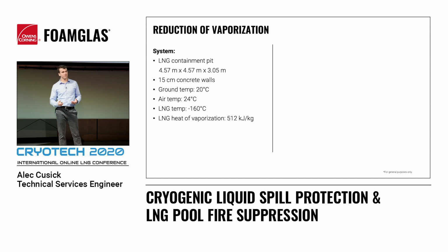One of the capabilities of our technical services team here at Foam Glass is the ability to run various energy analysis calculations for your specific pit and/or application. Here we have a hypothetical instance of an LNG containment pit that we're going to run an energy analysis report for. This LNG containment pit is about 4.5 meters wide by 4.5 meters long by about 3 meters deep. It has 15 centimeter concrete walls with a ground temperature of around 20 degrees Celsius, an air temp of 24 degrees Celsius, an LNG temp of negative 160 C, and you can see there the LNG heat of vaporization at 512 kilojoules per kilogram.